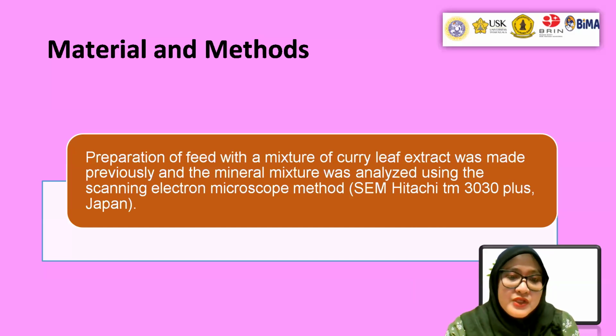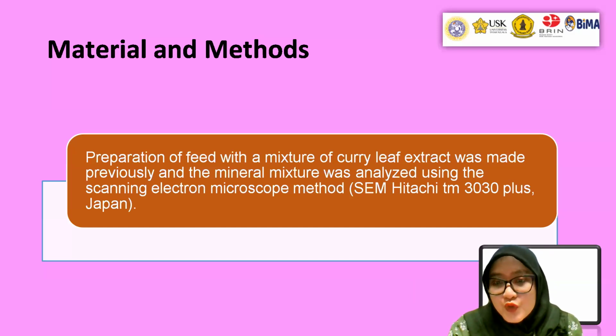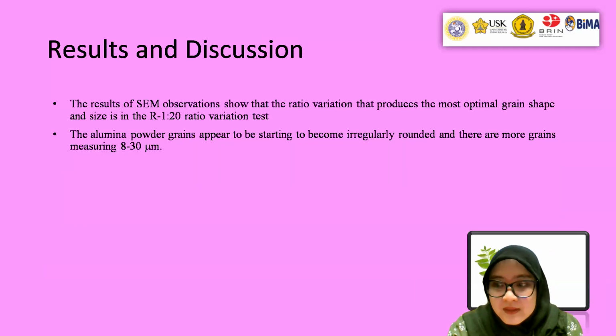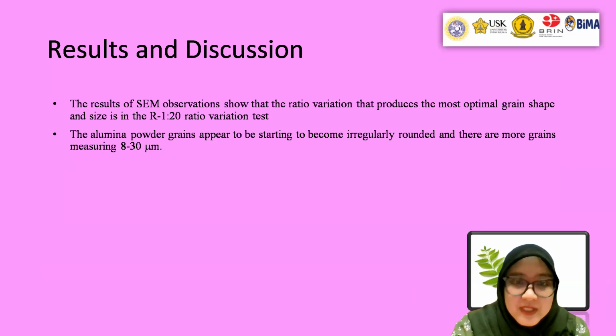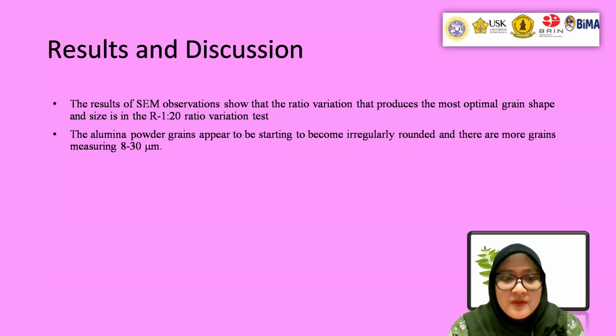So before preparation of feed, a mixture of curry leaf extract was made previously, and the mineral mixture was analyzed using the scanning electron microscope Hitachi TM3030 Plus from Japan. And then the result and discussion for this research: the observation shows that the ratio variation that produces the most optimal grain shape and size is 1 between 20 ratio variation test, and then the alumina powder grain appears to be starting to become irregular rounded, and there are more grains measured 8 until 30 micrometer.